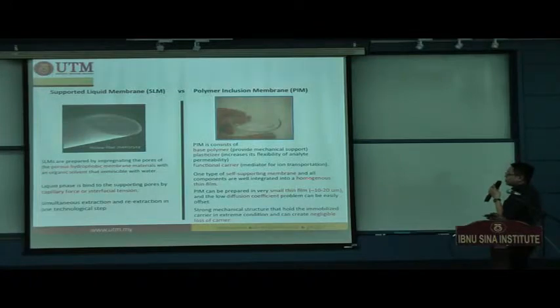This kind of membrane is a self-supporting membrane, and all components are well integrated into a homogeneous thin film. The thickness can be very low, down to 10 microns, which is absolutely perfect when we are applying this membrane in a microfluidic extraction cell. Because of the thin film thickness, the low diffusion coefficient problem facing thicker membranes can be easily offset, which means the ions are able to pass through the membrane much faster.